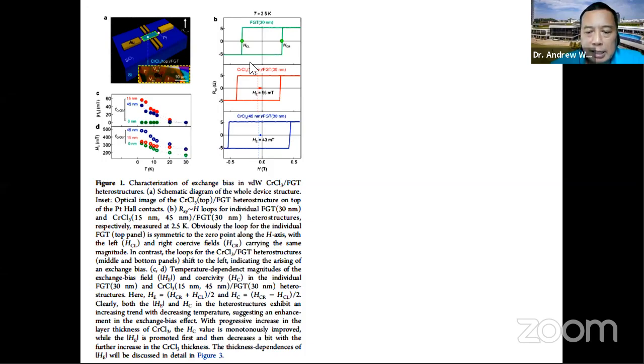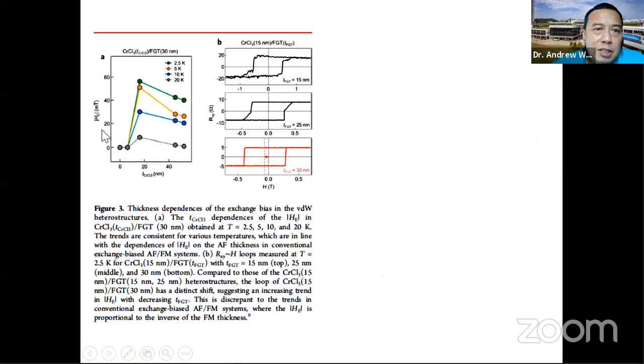As you can see, let me skip the details, you have the optimal level of this exchange energy at about 20 nanometers chromium trichloride on 30 nanometers FGT. So these are very thin films, not in a monolayer limit, in a few layer limit, because it's difficult to make these materials monolayer. But nevertheless, you see this exchange bias, and exchange bias basically breaks the symmetry of this hysteresis. You see this red arrow, you have a shift of the hysteresis to one side, that's the exchange bias.